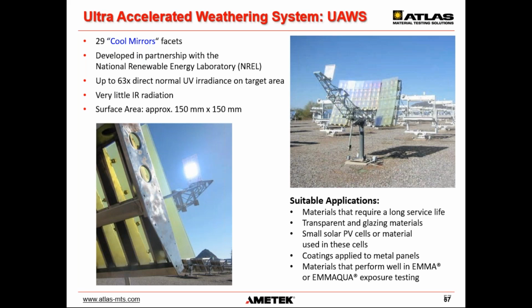These types of devices and this type of exposure have been good for something that has an extremely long service life, things like transparent glazing materials. The samples sit on a water-cooled panel that we see right here to help keep the temperatures in check. Sometimes we'll do testing for photovoltaic applications as well, and basically anything that performs well with the high intensification from either the traditional EMMA or EMMAQUA type of exposures can potentially be used for this. We have, I think, either 3 or 4 of these units that are now functioning at our DSET location.